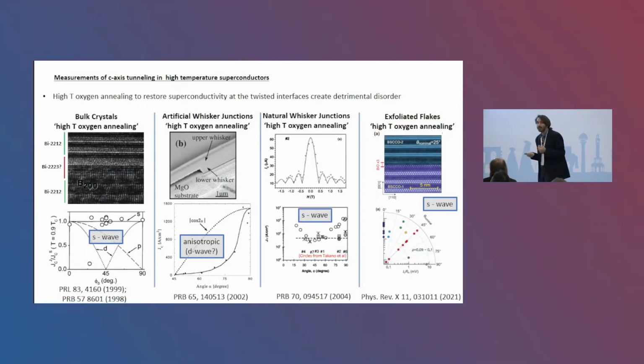First of all, realizing cuprate nano devices is difficult. It's really difficult, and for 30 years people have been trying to realize a C-axis Josephson junction. Now, what is the big deal? First of all, in-plane Josephson junctions have been realized, and that is how the superconducting order parameter has been measured. These junctions address Cooper pairs with a coherence length of about 2 nanometers, so you could be a little bit forgiven if you have some sort of disorder or meandering at the interface.